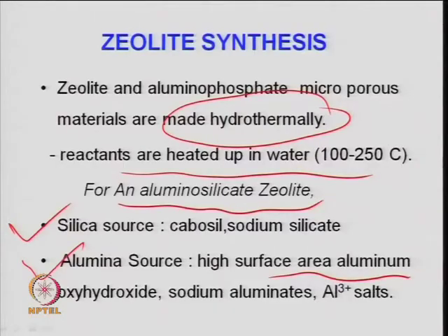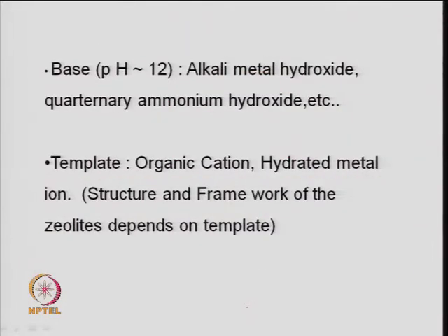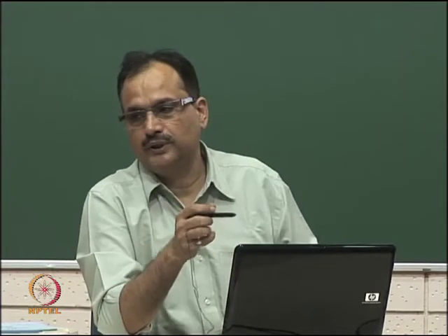So, any type of these materials can be used for this purpose. Then pH is very important. Generally the basic medium is desired, 10 to 12, and that again depends, because it provides the hydroxyl ion during the reaction, right. That is important when you look at the complex which forms during the reaction, and the structure which builds is a function of the pH also, right.